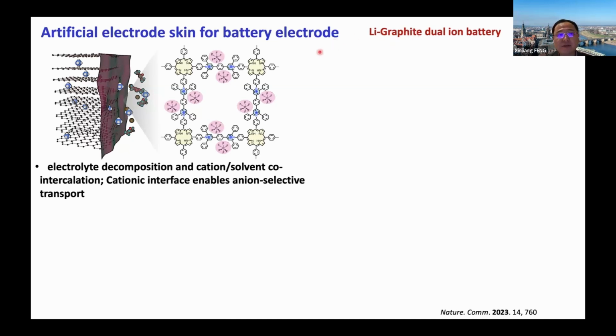And for the graphite cathode, we need the counter anions for the intercalation chemistry. So this tetrafluoroborate is a very big anion that needs to intercalate into the graphite interlayers to boost the energy storage. And on the anode side is the lithium stripping and plating process. The problem for this intercalation chemistry with the large anion into the graphite is that you end up with electrolyte decomposition due to the larger anions, and also you have the cation-solvent co-intercalation, which is a bigger problem.